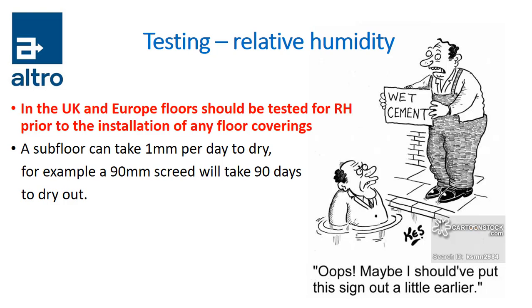So, testing for relative humidity. In the UK and Europe, floors should be tested for RH, relative humidity, prior to the installation of any floor coverings. So for example, a subfloor can take 1 millimetre a day to dry. So if you have 90mm screed, it's going to take 90 days to dry. Power floats, because of what you've done to it, closing the surface with the machine, can take actually longer. And I think the guy on the right hand there is, I hope he gets out there before he gets set in there for life.